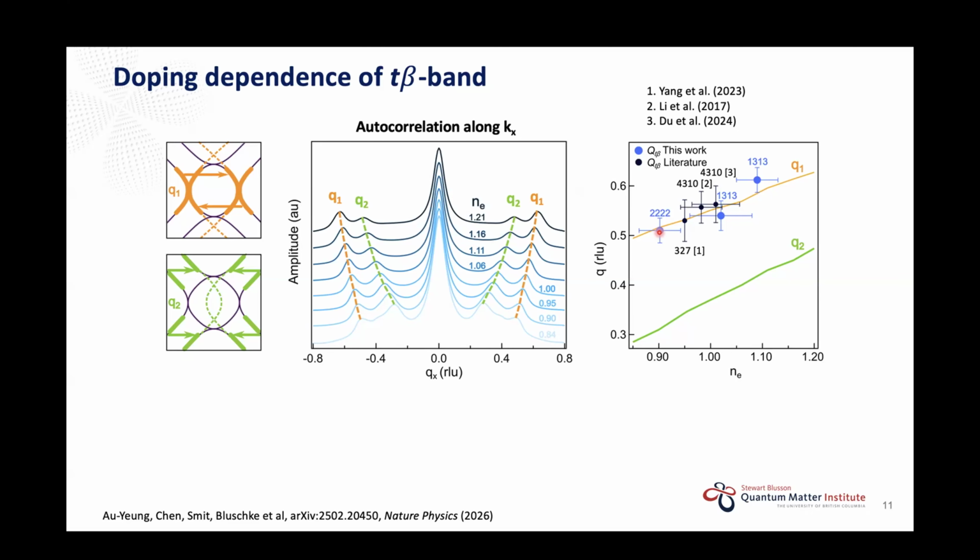Anyway, it had to do with the difference in TC between the tri-layer, shall we say, and the bilayer. That of course could be. If we think the outer layers in the tri-layer are the superconducting layers, there could be superconducting pairing within each of the two outer layers. They could be two superconductors which are weakly coupled in the case of the tri-layer, but in the case of the bilayer, they could be much more strongly coupled.